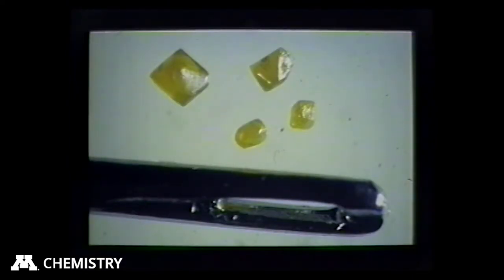And in the same series of borate dyes here, we have some yellow crystals which are showing the first signs of reaction. Notice that some of the edges are a little bit dark, and the surface of the crystals are somewhat mottled. A few hours prior to this, these crystals were highly transparent, and they had none of those effects of partial reaction showing at all.